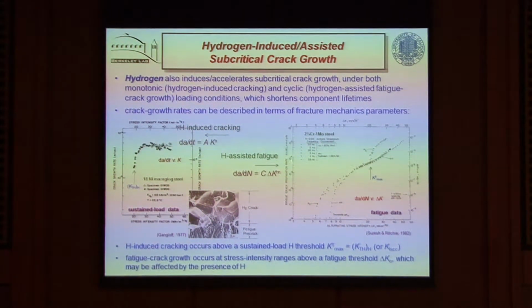And under fatigue, of course, we have the same sort of curves. Now, instead of dA/dt, this is dA/dN as a function of the range of the stress intensity. So we have these two different types of VK curves, dA/dt as a function of K, and dA/dN as a function of delta K. Now, in fatigue, you can see they get rather complicated. They have a sigmoidal shape, but in presence of hydrogen, we get these accelerations. We get an acceleration due to hydrogen at low stress intensities, approaching a so-called threshold, and we get accelerations at higher stress intensities above another threshold, which I've called KT max. And in a high-strength steel, this threshold is the one we measure under sustained loading. And so this has led people to think that there may be a superposition of these types of behavior. This is the sustained loading, this is cyclic loading, and we can simply superpose this data on top of fatigue under a non-hydrogen environment and predict what's happening in fatigue in hydrogen.